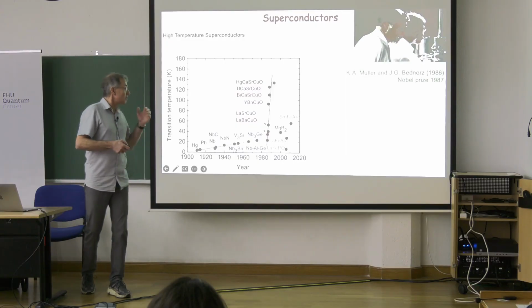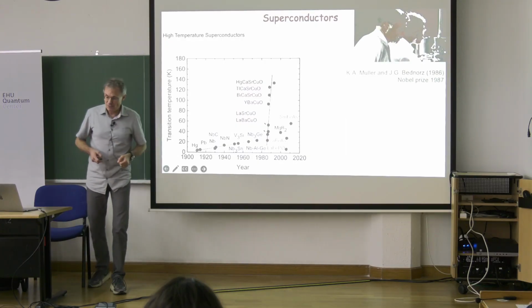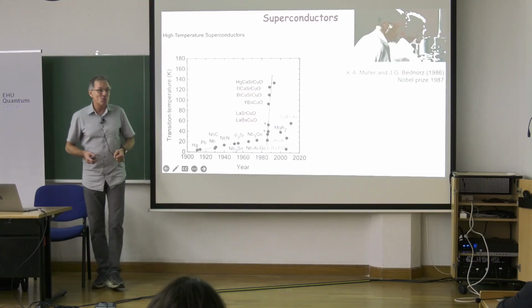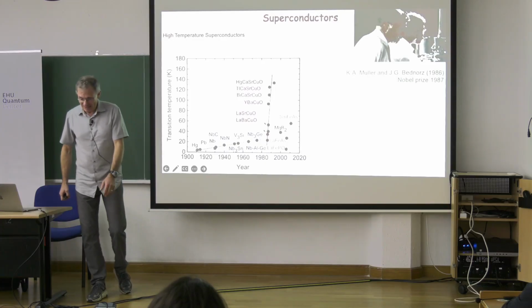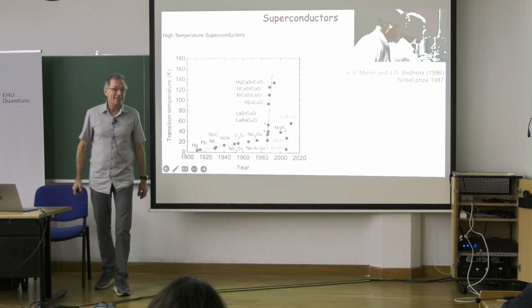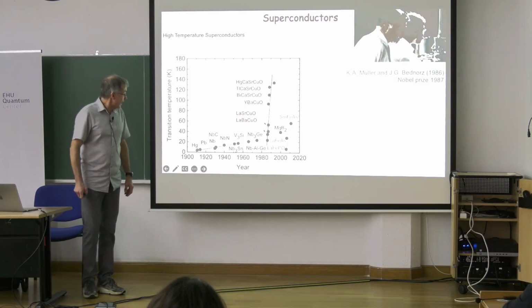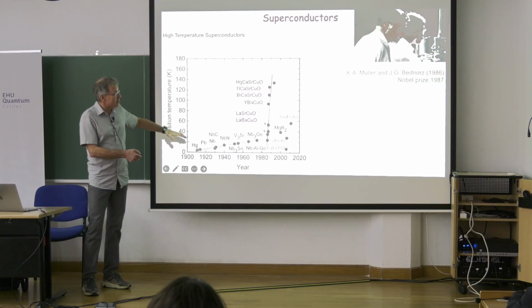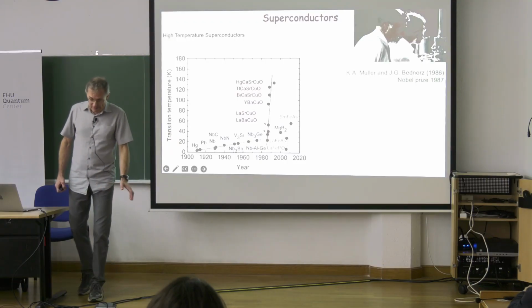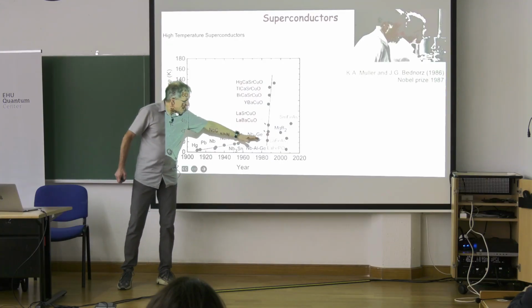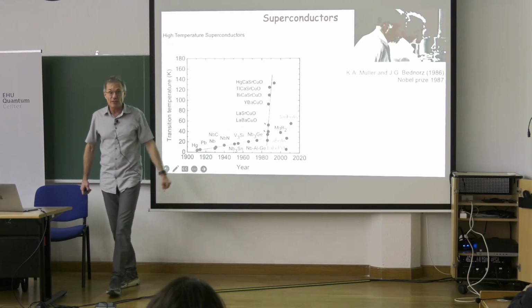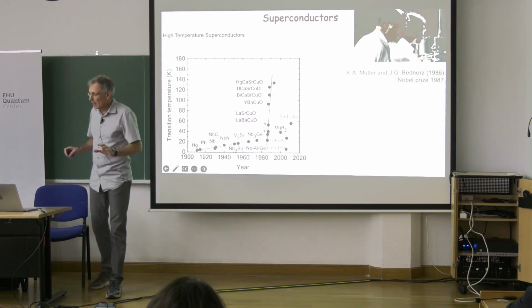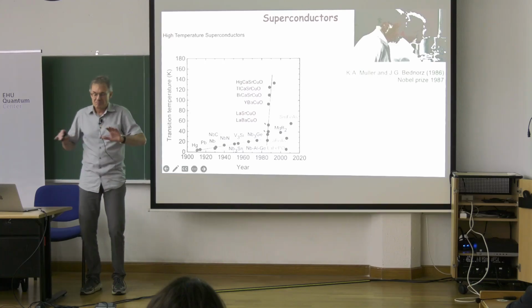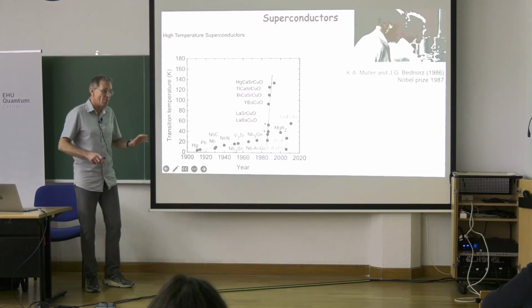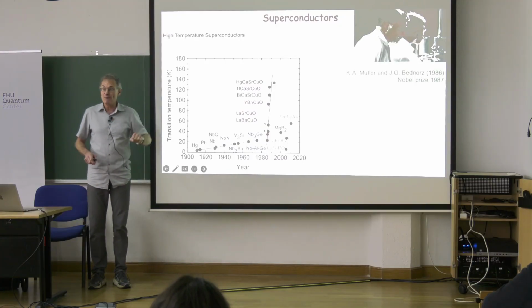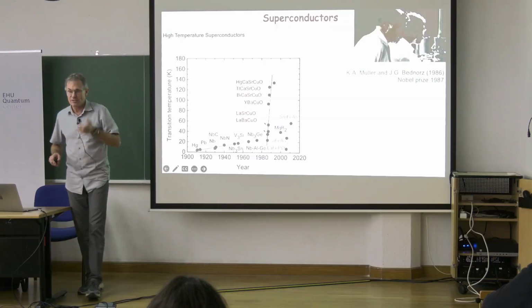Then the next step was almost 40 years ago, but well, I still remember that time. Eugene and I were students, we were starting our PhDs when this was discovered. And actually, till 1986, people tried to increase transition temperature and managed something like 23 or 24 Kelvin. They tried hard, and the transition temperature didn't go up, and there were many theories which said that there is a fundamental limit, that you cannot have superconductivity with Tc more than 30 Kelvin.